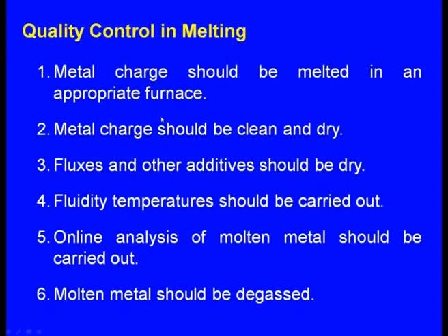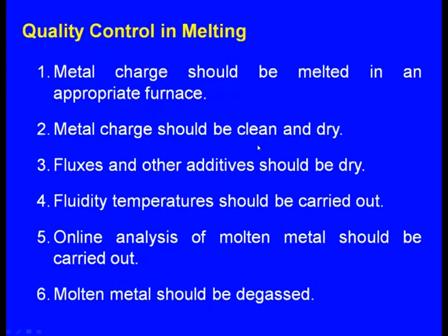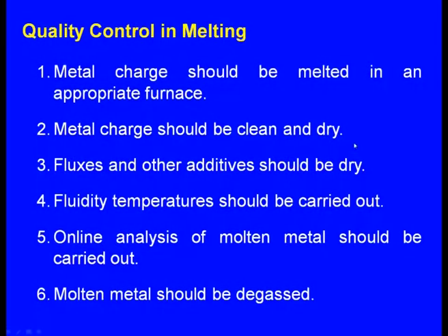There are different furnaces available, we have already seen, and an appropriate furnace should be taken. Next one, metal charge should be clean and dry. Sometimes people take the scrap and dump it in the furnace, and this scrap may contain unwanted oils, lubricants and so on. Then the composition will change, or hydrogen will evolve because of the carbons or hydrocarbons present on the surface of the scrap. So, the metal charge should be clean and dry.